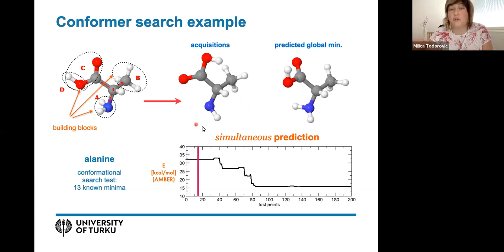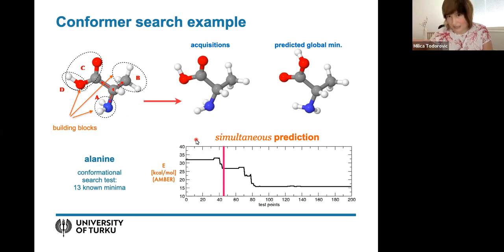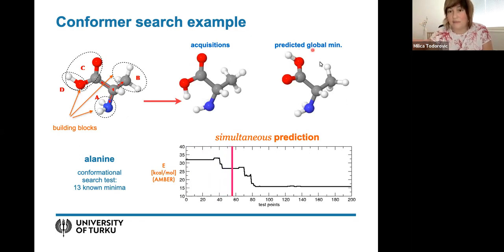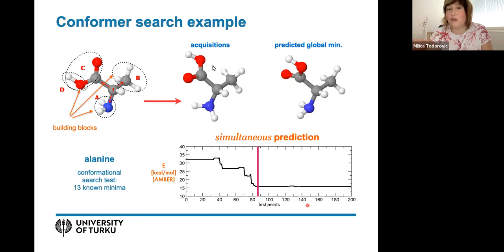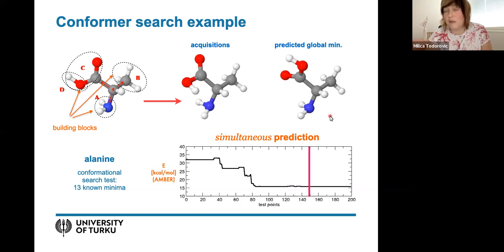And again, you see how this works for a molecule. With four different torsional angles, the BOSS is simply sampling many different structures and again building the energetics models in 4D. And from here, you see the current prediction for the global minimum. And here you can see how the energy of this structure varies as we sample more and more configurations. In the beginning, the prediction is not very good, but then as we see more configurations, the energy goes down in plateaus. And then after about 90 structures we have seen, the energy no longer changes. And now this is the final structure of the global minimum. And indeed, if we look at the literature, this is the one.